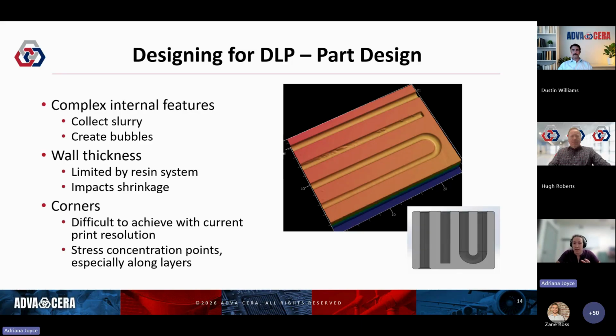The raw material that we're working with is a suspension. Ceramic particles are suspended in this photopolymerizable resin. So the ceramic component is 40 to 60% of the green part, which means that we are burning off a large concentration of organic material. As that decomposes, the organic has to leave the part, and we want that to happen without damaging the part. That limits our wall thickness. Depending on the resin system and the ceramic percentage, the maximum wall thickness in the sintered state can be as little as 4 millimeters or as large as 10, but it's slurry and design dependent. So that's something that we like to work with customers from the beginning to address.